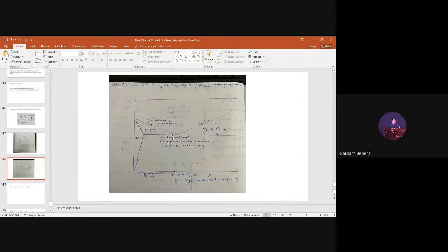Anyways, you can see in spheroidizing annealing, recrystallization annealing, and stress relieving annealing, the temperature is below A1. So below A1 means no phase transformation is happening. There is no phase transformation involved here, right? I think you have got the answer. But in full annealing or normalizing, there will be a phase transformation. The initial phase is austenite, and if you cool it, it will transform into pearlite or some other phase depending upon the rate of cooling. So phase transformation is involved in this case, but here there is none because we are neither hitting above A1 nor above A3 or ACM.